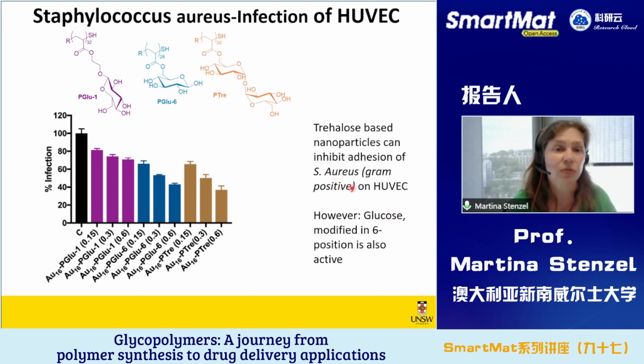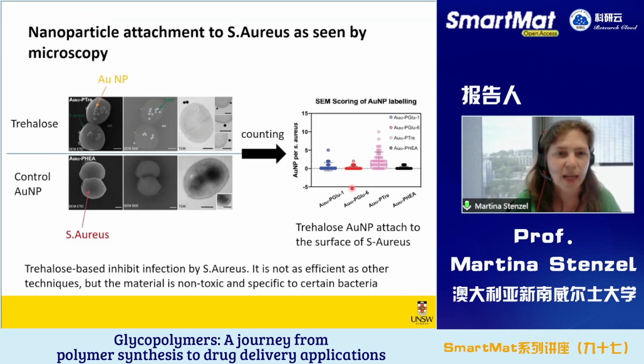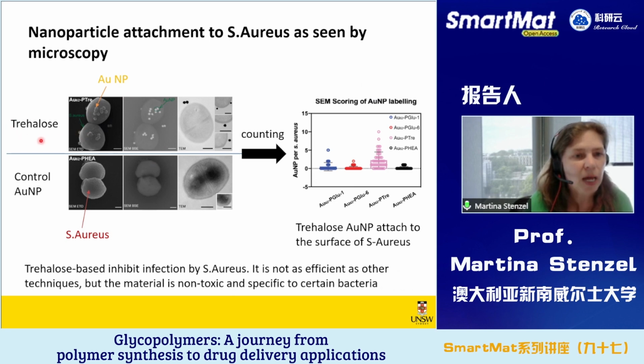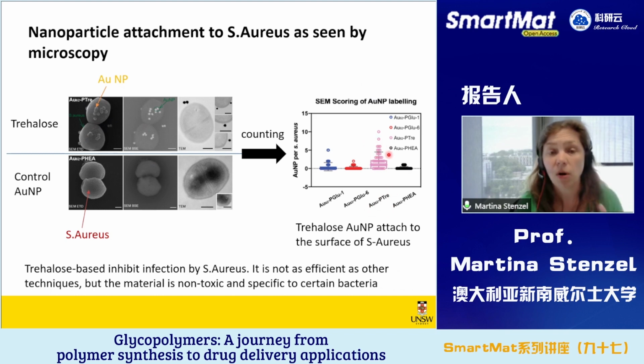Golden staph is a very common infection, very often found in hospitals. To really understand it a little bit more, we looked under the microscope and we found how trehalose gold nanoparticles really attach to the surface of the bacteria, and they glue very strongly to it. When we look at the amount of nanoparticles per bacteria, we found that trehalose particles bind very, very strongly to these bacteria. And because we have these trehalose particles attached to the bacteria, it cannot invade HUVEC cells anymore, so healthy cells.